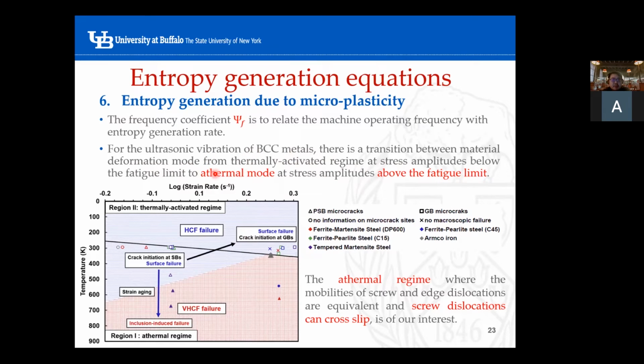And these two deformation patterns actually have different micromechanisms. For example, at athermal mode, which is where our ultrasonic vibration belongs to, at this mode we have the mobility of screw and edge dislocations being equivalent, as screw dislocation can cross slip.